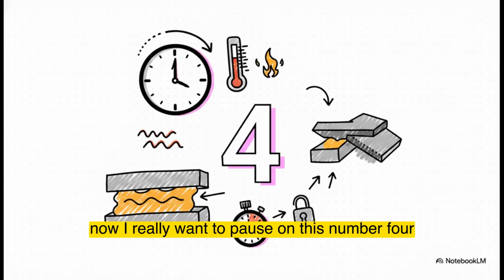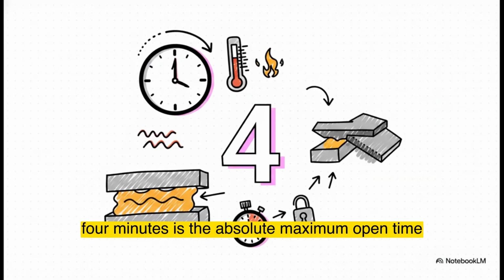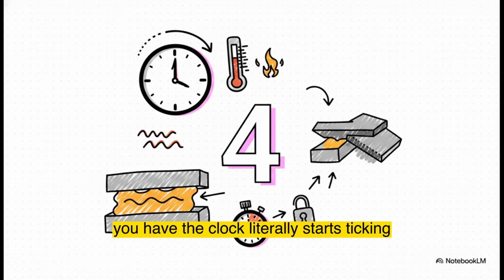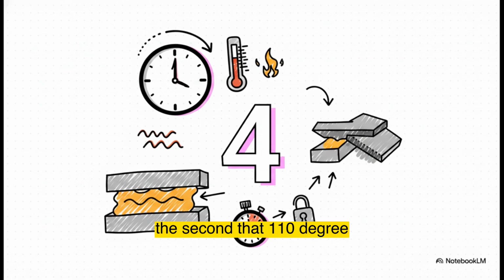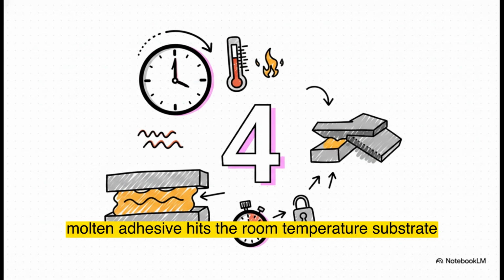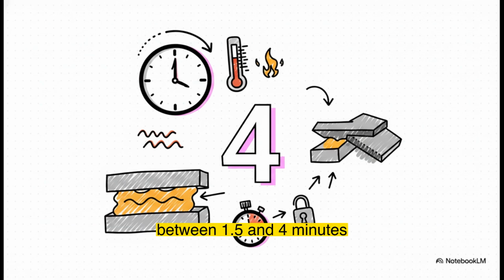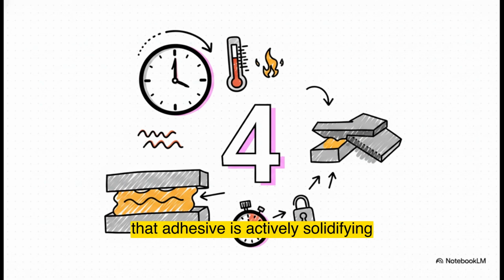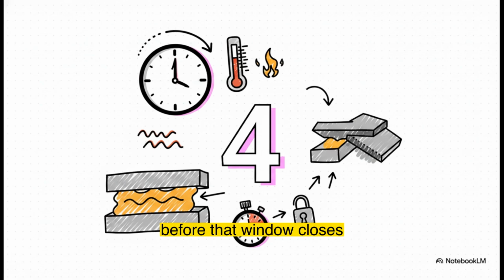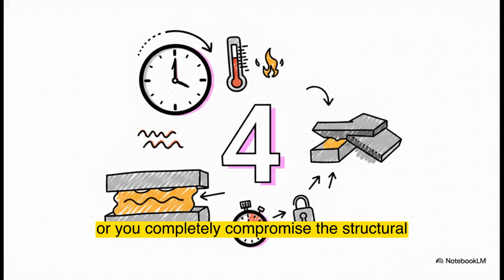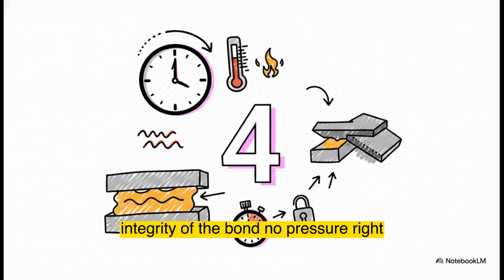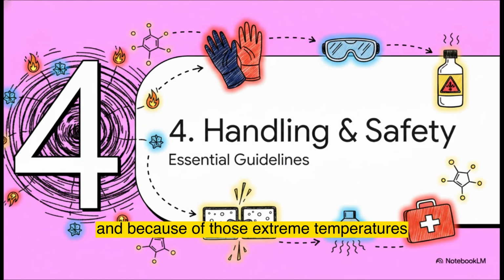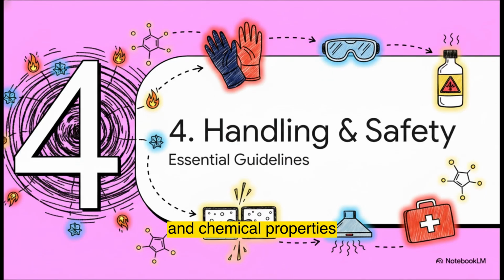Now, I really want to pause on this number, 4. 4 minutes is the absolute maximum open time you have. The clock literally starts ticking the second that 110-degree molten adhesive hits the room temperature substrate. Between 1.5 and 4 minutes, that adhesive is actively solidifying. You have to join those substrates before that window closes, or you completely compromise the structural integrity of the bond. No pressure, right? And because of those extreme temperatures and chemical properties, Section 4 is absolutely critical.